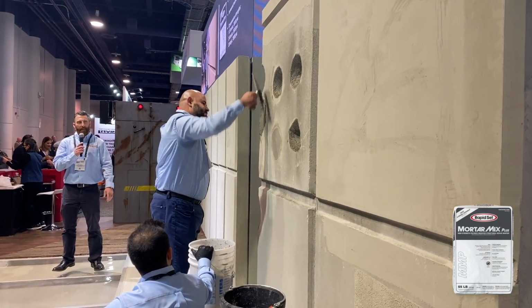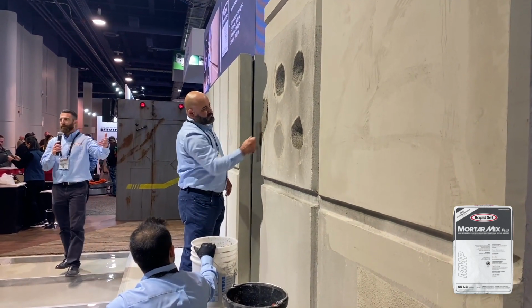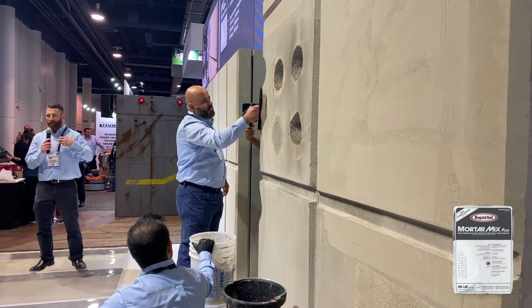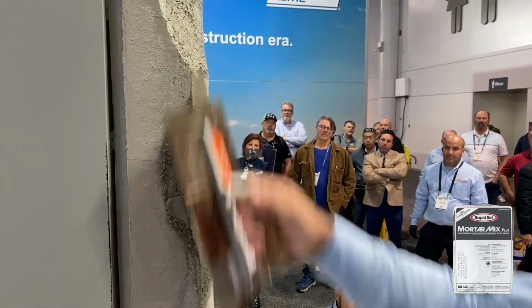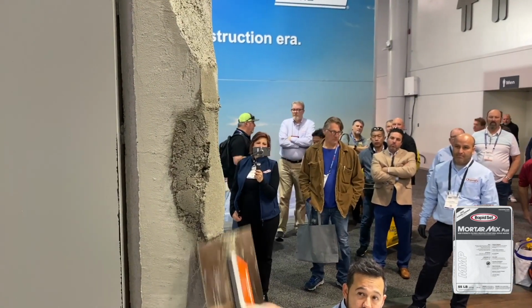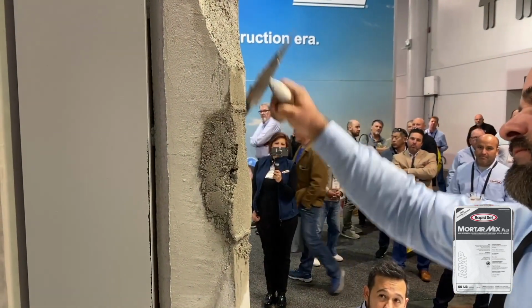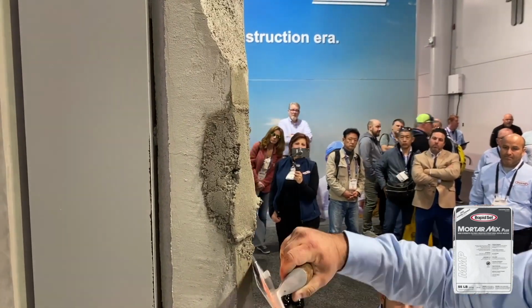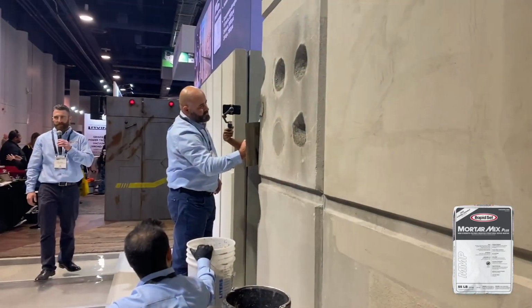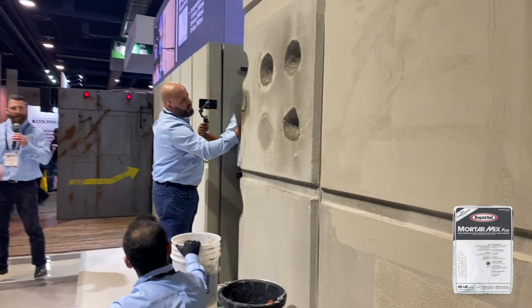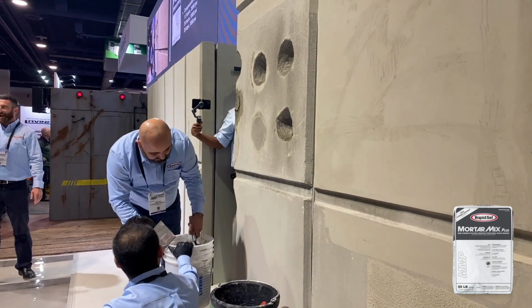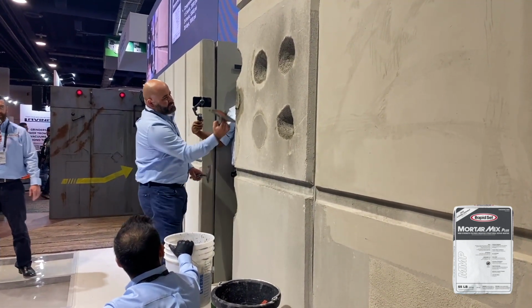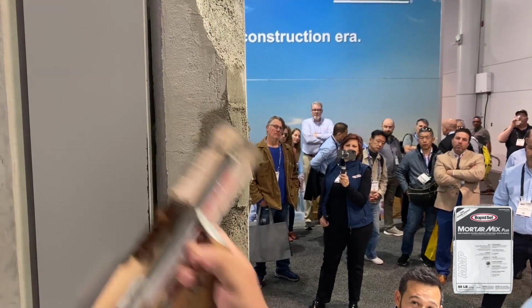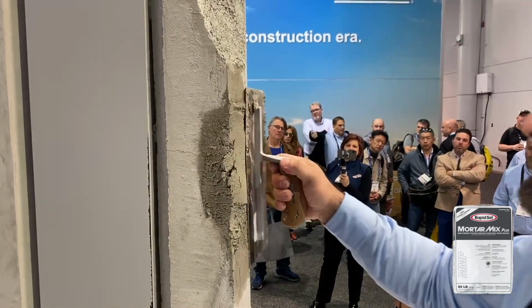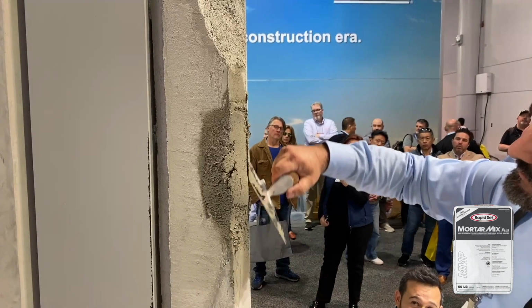If you saw earlier, they actually pre-wet the surface, and the purpose of that is to fill the pores in your substrate, so that way you don't lose your mixed water into the substrate. So that gives you better adhesion and better strength. Again, if you're familiar with our mortar mix in the brown bag, this is a little bit different. We've given it extra working time, but it still gets structural strength in about an hour and a half, gets 2,000 PSI, and will achieve 7,000 PSI in 28 days.